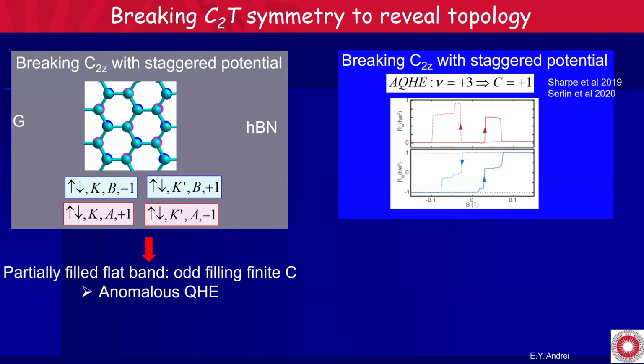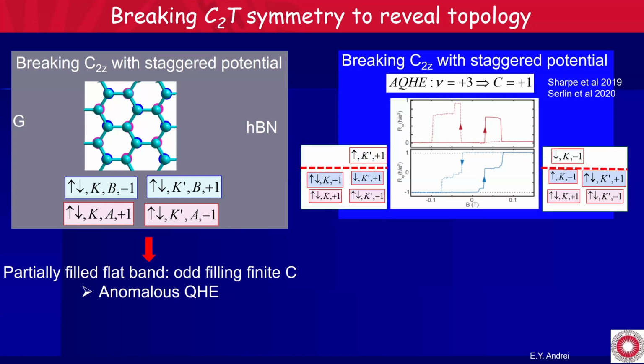They change the orientation of the magnetic field. The hole in one case sits in the K valley, and in the other case sits in the K prime valley. So you've switched valleys. So of course you see the quantum anomalous Hall effect with the 2 different values. So this is all very beautiful, and it agrees with naive theory, but that's when Allan and other people notice, wait a minute, how can that be possible?